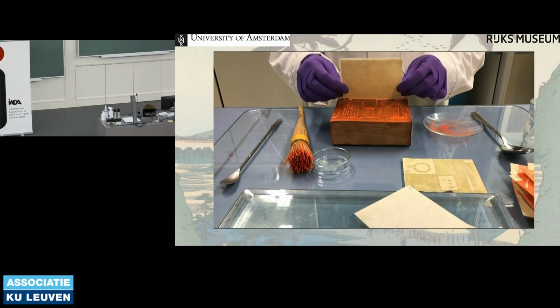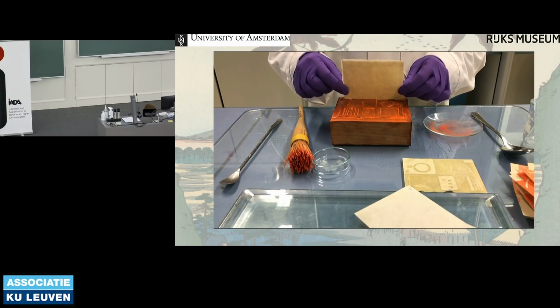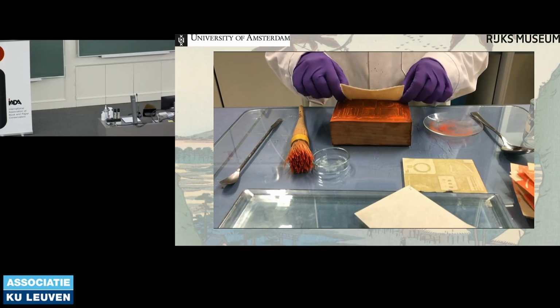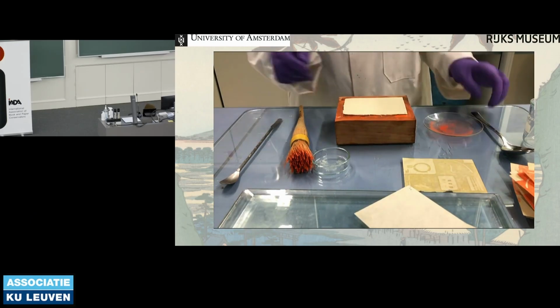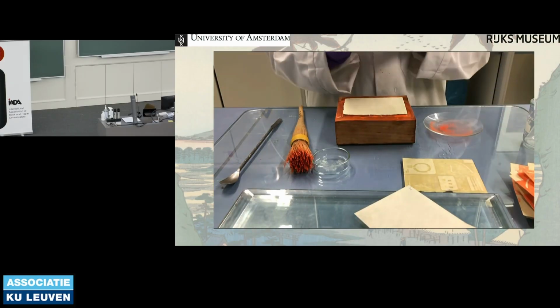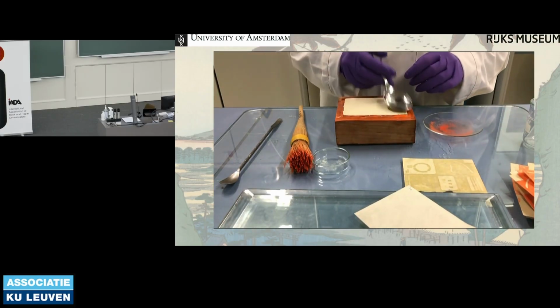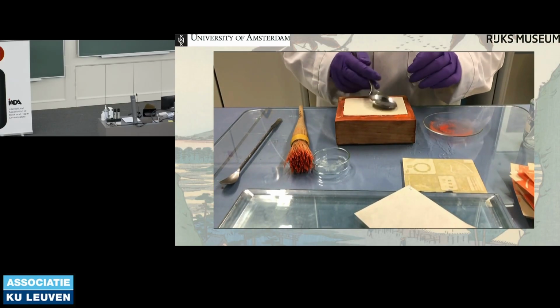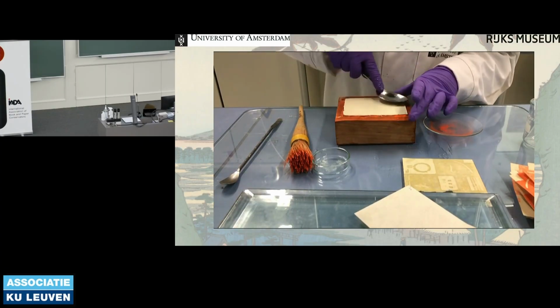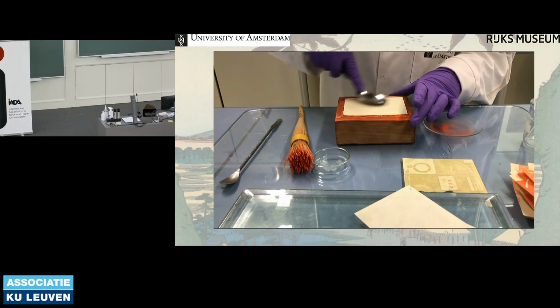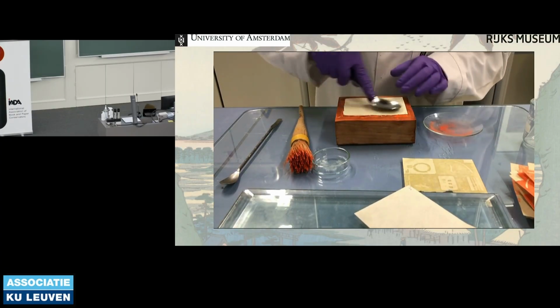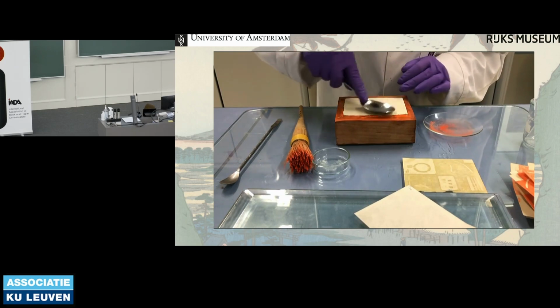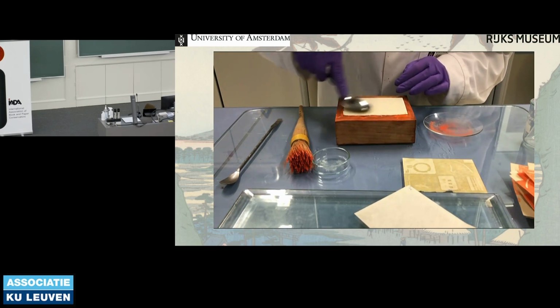You place it down, and then I'm going to use a very complicated tool for the rubbing, which is a tablespoon, recommended to me by a local Dutch printer. And I'm not going to show you the very end product because I rub for approximately 2 minutes straight. But you end up with a print that looks like this.